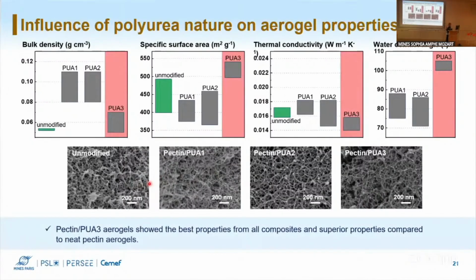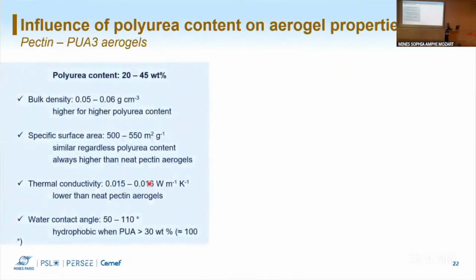Overall, we concluded that the third type of polyurea worked the best, so we decided to go with it. And also, we tested the aging and we saw that it had better stability in moisture. So going with the third type of polyurea aerogels, we wanted to see what is the influence of polyurea content and how much we can reduce the synthetic polymer inside the material. We worked with polyurea content from 20 to 45% in the dry material.